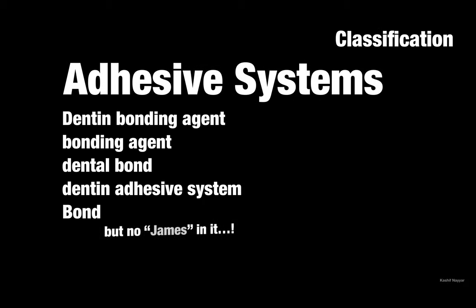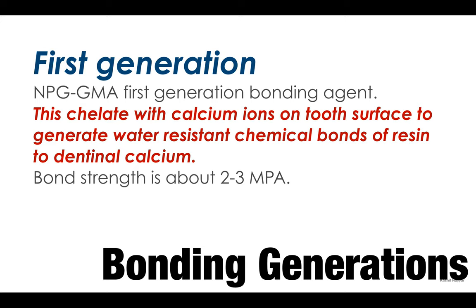So let's go to the classification of the adhesive system. The adhesive system is the dentin bonding agent, the bonding agent, a dental bond, or dentin adhesive system, a bond, but there is no James in it, okay? So our first generation of bond was based on the method where the calcium ions were chelated on the tooth surface while creating a water resistant layer. Unfortunately, the bond strength was no more than 2 to 3 megapascals. So it was, of course, obsolete.